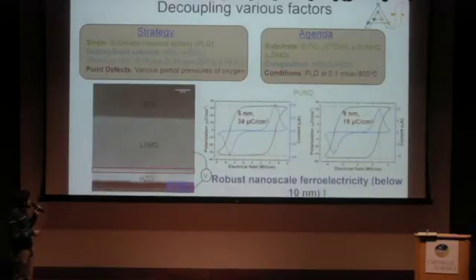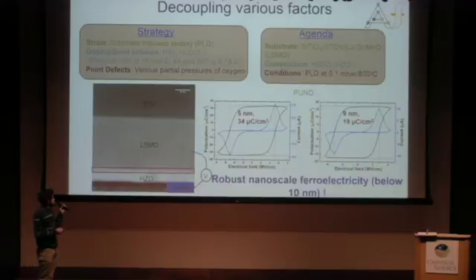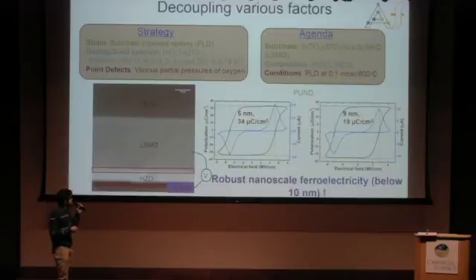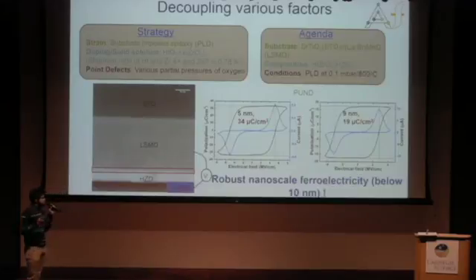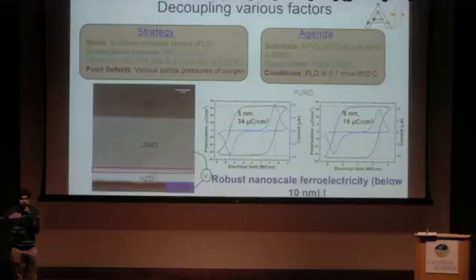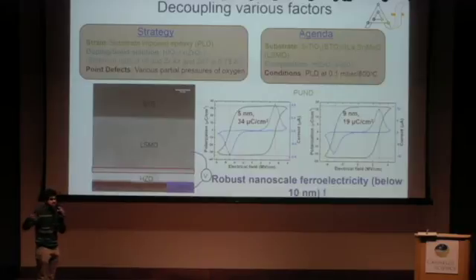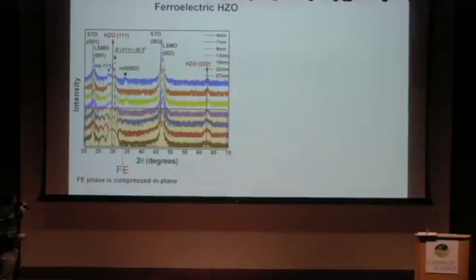But however, when you put another symmetric electrode and then measure the polarization electric field hysteresis, you do PV hysteresis, you do in fact see that for films which are thinner, 5 nanometer films, we measure a higher saturation polarization of around 35 microcoulomb per centimeter square compared to the thicker films. So this is true. Thinner it gets, the smaller the size gets, the better is the PV hysteresis. So there is some new kind of ferroelectricity, or different from what happens in conventional materials.